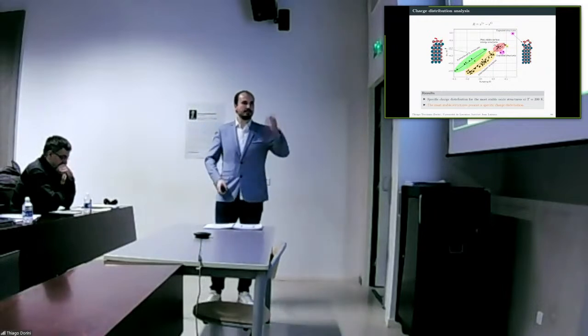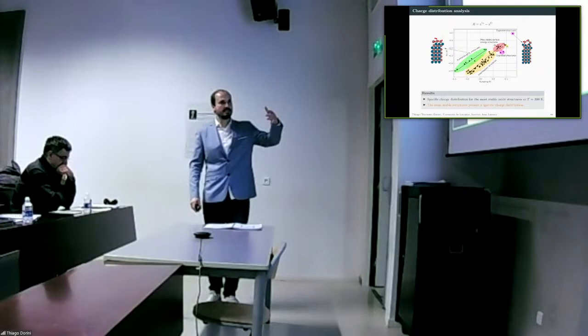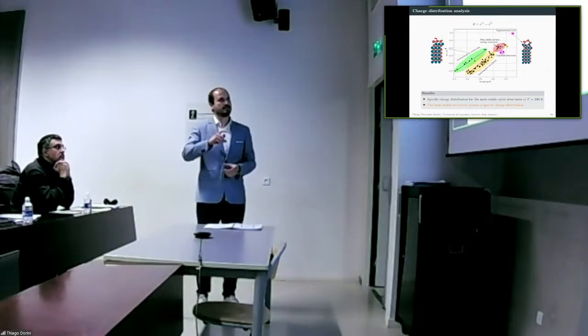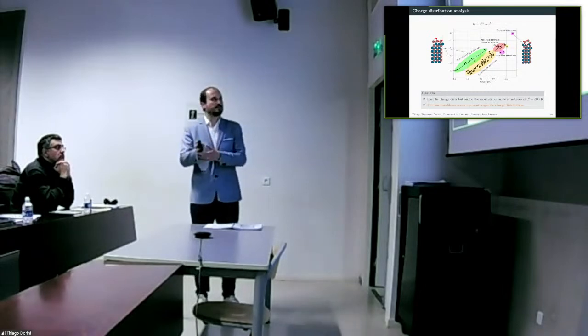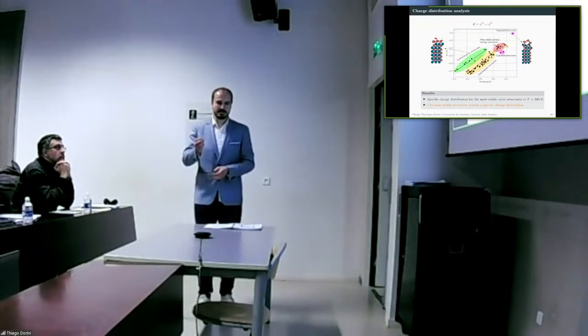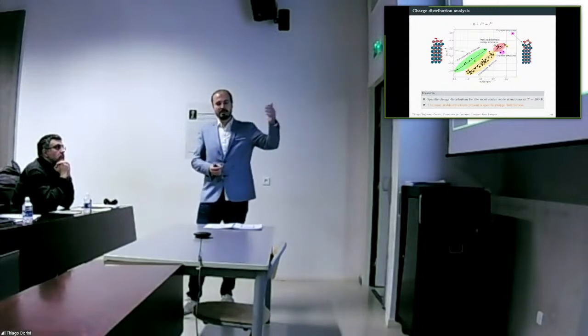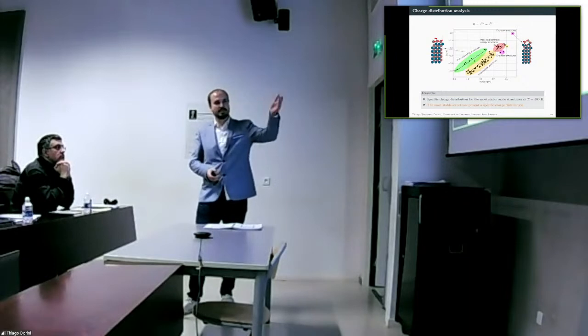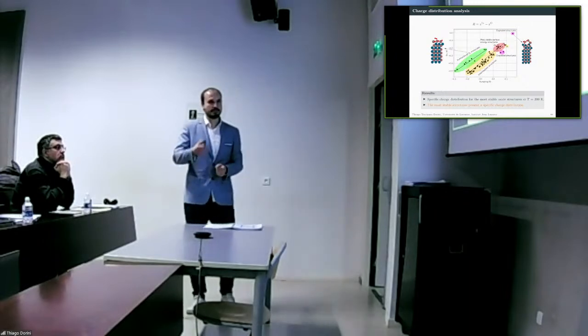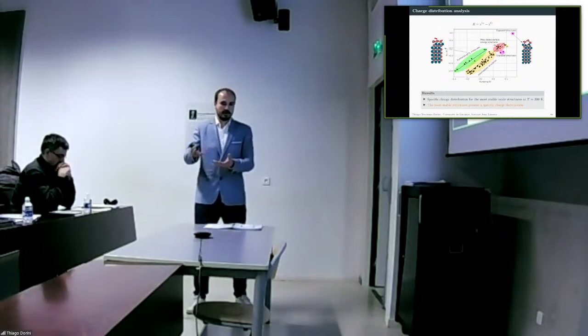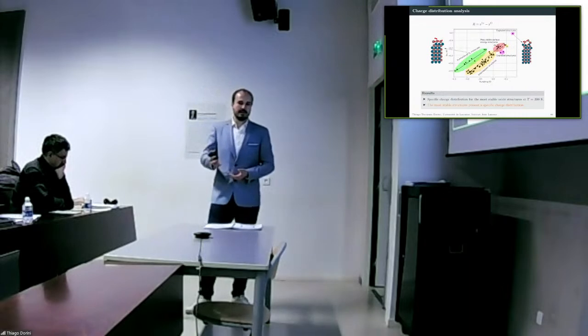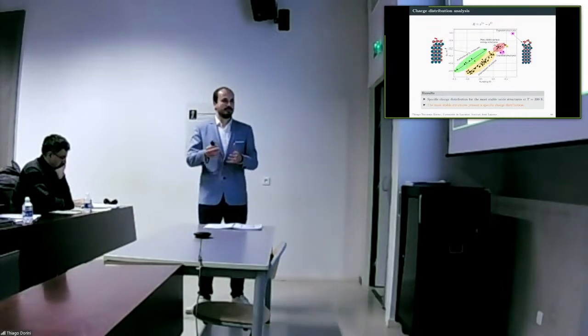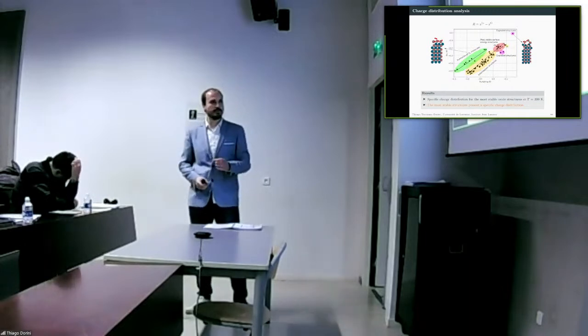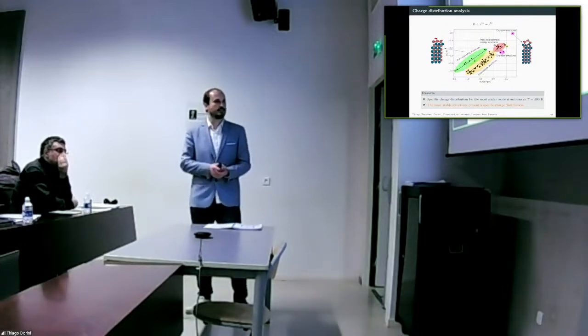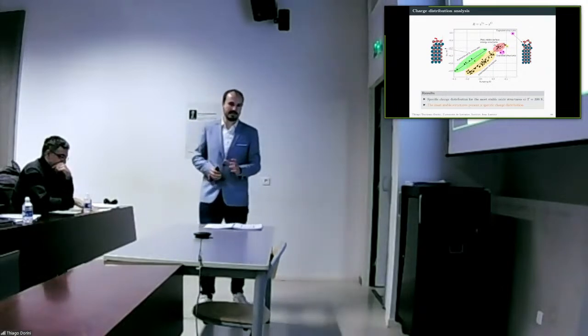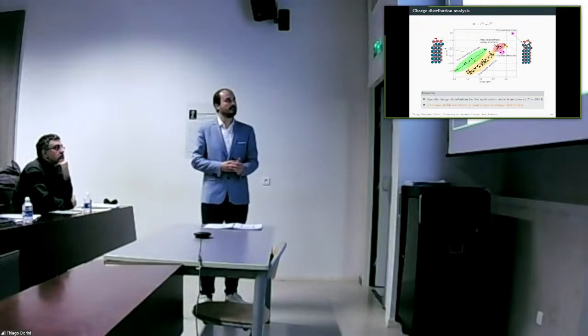So the idea is basically, after we have selected the best structures, we see that they are stable, and we correlate the atomic configurations that we have selected according to their structures. What I'm trying to say is that only by looking at the structure of these oxides, especially the indium oxide systems, we could have an idea about their stabilization and many other properties, such as the STM images. Probably the charge distribution would be a bit more challenging, but only by knowing the atomic configuration of these oxides may lead us to some properties. This is what I meant at the beginning of the work.